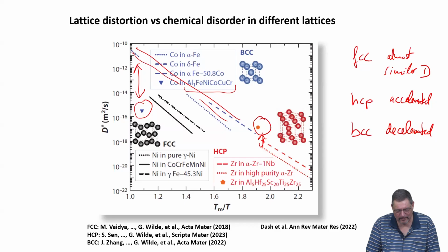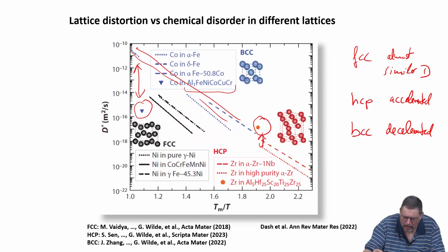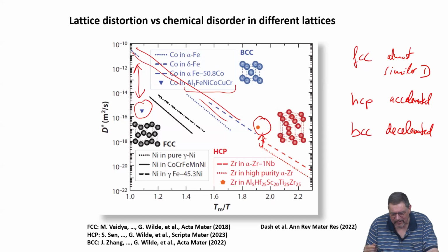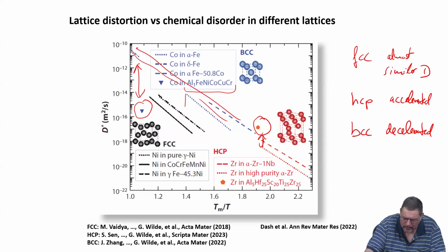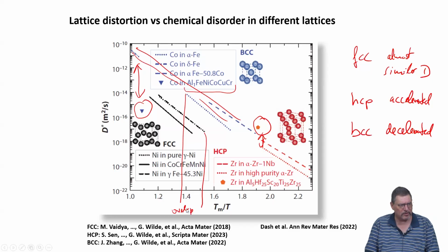The temperature is also there, like homologous temperature. Like in FCC, it's diffusion at very high temperature. BCC, yeah, there are slight differences, but you see there is a strong overlap here, between FCC and BCC temperatures on the homologous scale. So it's not such a big difference, and you see the Arrhenius plots are straight, they go continuously, you don't see a kink or anything like that. So it means the mechanism is probably unchanged for each crystal system over this range of temperatures.